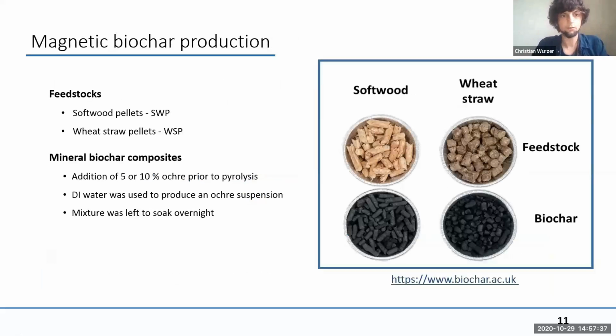To study this, we used two different feedstocks, softwood pellets and wheat straw pellets, and mixed them with 5 and 10% of ochre prior to pyrolysis, which means we added around 2.5 and 5% of iron, so not a lot. You can see the feedstock on the right.